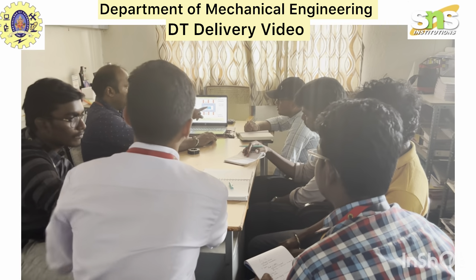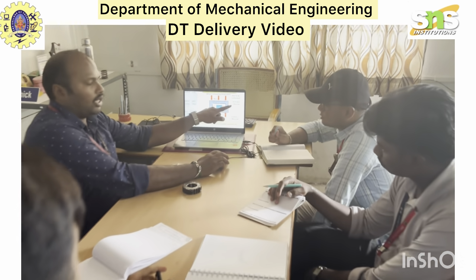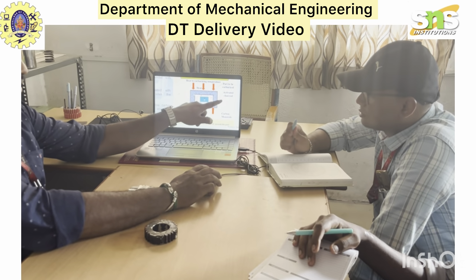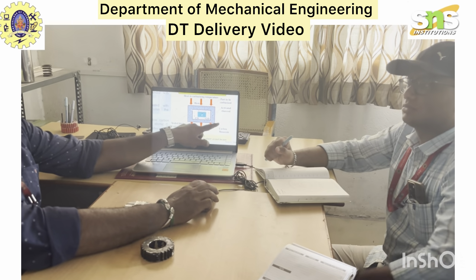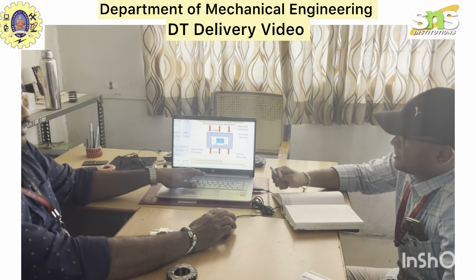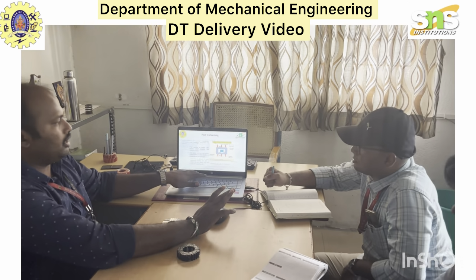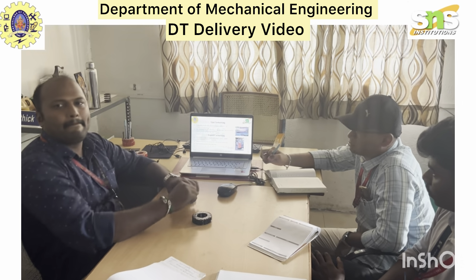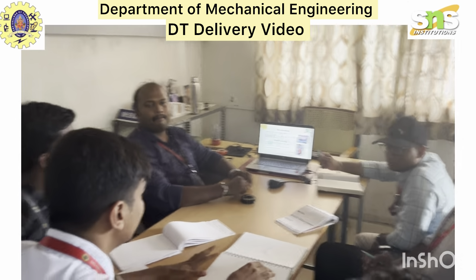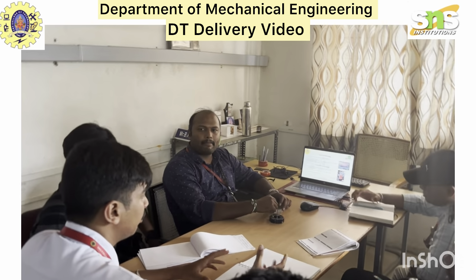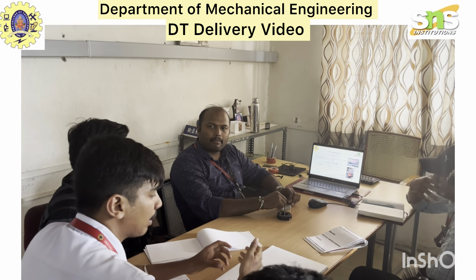Here you can see the activated charcoal, which is activated through barium carbonate. The carbon inside this charcoal will be imprinted on the outer surface of the part which we are going to carburize. Next is gas carburizing, in which the metal which we are going to carburize is heated up to 930 degrees Celsius.